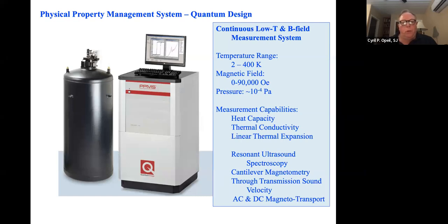That cylinder you see at the right is a Dewar. It's basically a big thermos bottle, and in the thermos bottle is about 100 liters of liquid helium, and I recycle the liquid helium so I can stay cold for about 2 years. The measurement capabilities that are really important here are heat capacity, thermal conductivity, and linear thermal expansion, because I can vary the temperature range at low pressure to measure them. There are many things that I've done in the past, particularly with thermoelectrics and other materials.